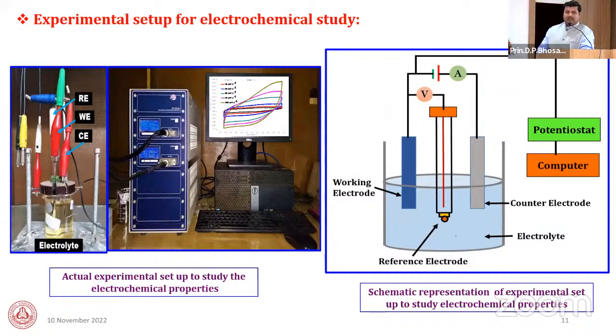When I studied the electrochemical behavior of this prepared cobalt phosphate material, I used a high-end electrochemical workstation, and this is the schematic diagram of the three-electrode cell system. In this system, three electrodes are used for testing electrochemical performance. This is the working electrode, which means our prepared material electrode. This is the counter electrode, a platinum plate, and the middle one is the reference electrode. With respect to the reference electrode, we tested the voltage of our material.